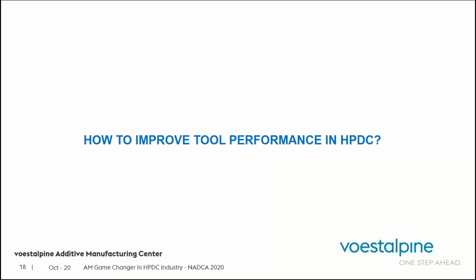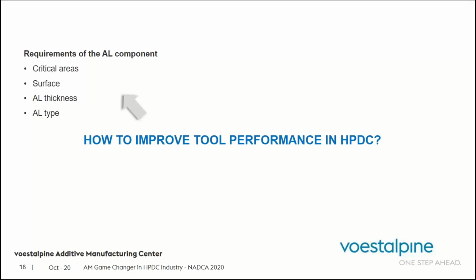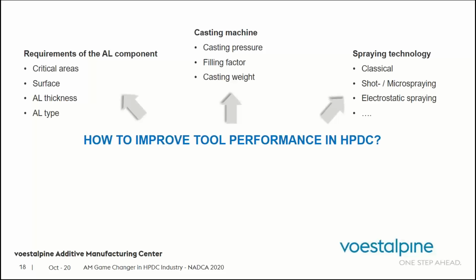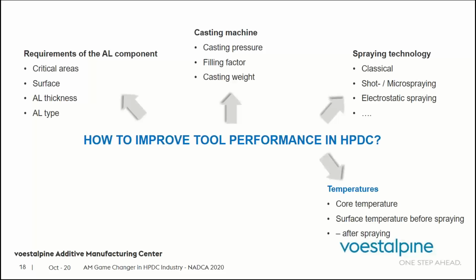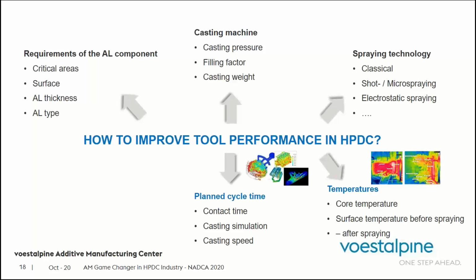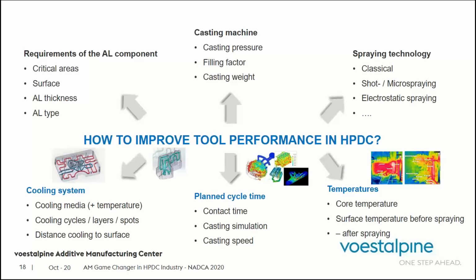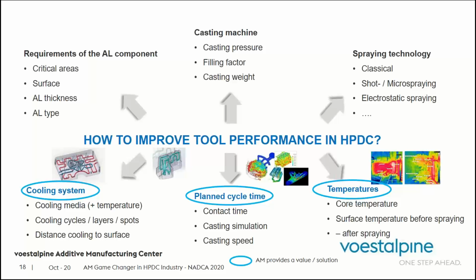So how do we improve the tool performance in high pressure die casting? There are multiple aspects that you can work on. One of them is the requirement of the aluminum component. Another one is the casting machine itself, including the casting pressure, the filling factor, and casting weight. Another one is the spraying technology, micro spraying or the classical. Also the temperature, the core temperature, the surface temperature before or after spraying, the planned cycle time, the contact time, casting simulation, and casting speed. Last but not least, the cooling system: the cooling media you're using, the cooling cycle, and the distance of the cooling to the surface itself. If you look at the bottom three, these are the three categories where additive manufacturing provides a value or a solution in improving the performance of high pressure die casting: controlling the temperature, the planned cycle time, and the cooling system as well.